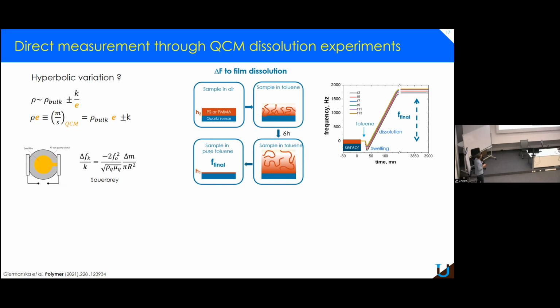We spin coated PS or PMMA on the quartz sensor with the thickness H2. We put it in the QCM. We actually use toluene because it's a very good solvent of both polymers. And basically what we did is that we dissolved the layer completely. So after, let's say, 6 or 7 hours, all the film was removed, not completely because there is always a very small layer that we call the irreversible layer that is always adsorbed. And this layer is around 1 nanometer. And so here you have a typical QCM signature.